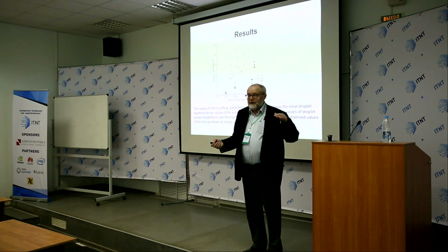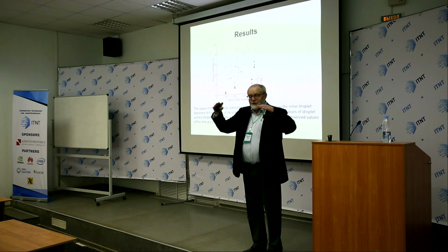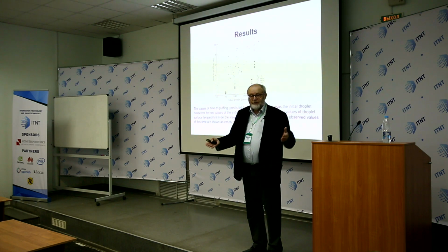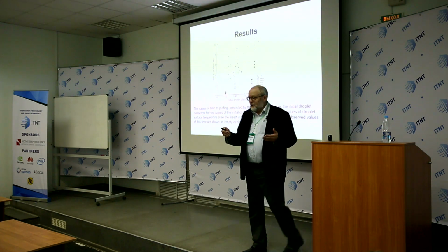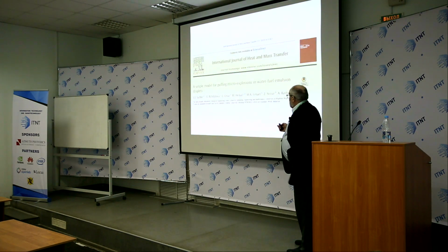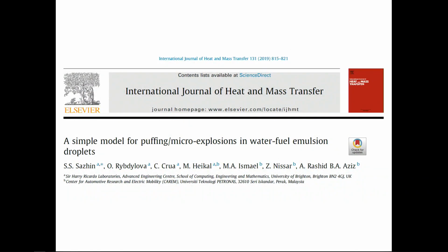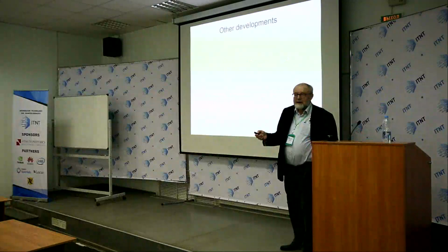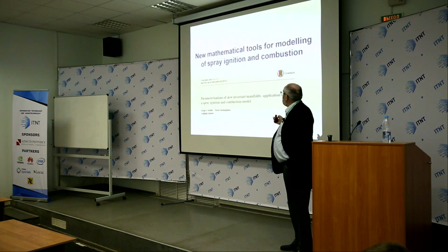And this minimal value of time to puffing is due to the fact that we didn't take into account the initial heating of the droplet, but we assume that the temperature of the droplet immediately reaches almost the boiling point. And then these results were published in the International Journal of Heat and Mass Transfer early this year. And these include our co-authors from the University of Petronas. And then I will just summarize briefly some other developments in the field.